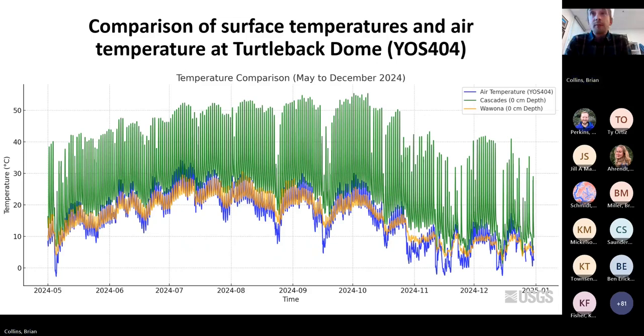I compared the surface temperatures and the air temperature of the nearby station that is located at the Turtleback Dome. You can see that the air temperature coincides quite well with the north-facing slope, but it's much lower than the south-facing slope. And this suggests that when assessing the influence of high temperatures on rock triggering, for example, we have to take this into account, because usually we are limited to using only air temperature as information, but we have to take into account that the rock can be heated, I don't know, twice as much if it's south-facing.